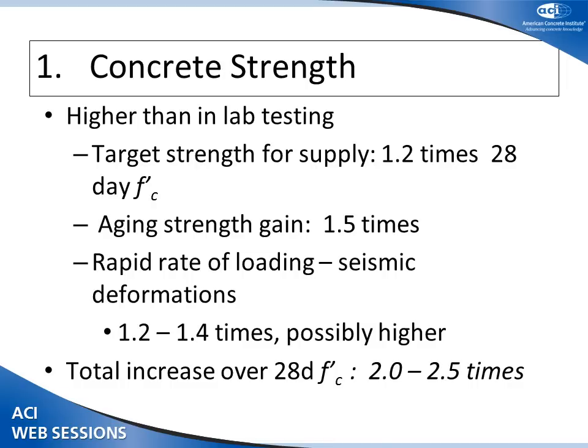Concrete strength. The concrete strength we are seeing in structures is obviously higher than the lab concrete that we've used to develop our engineering equations and recommendations. For a start, a supplier of concrete will be targeting about 20% higher than the engineers specify. Age enhancement of strength is about 1.5 times the strength. You'll find that under dynamic loading, the concrete, particularly the tensile capacity, can be 1.2 to 1.4 times larger. That means that the compressive strength can be anything from 2 to 2.5 times.